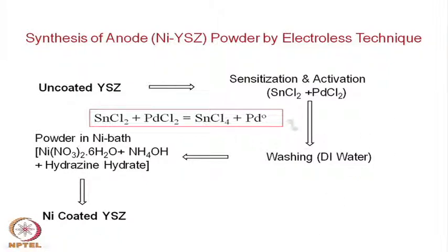Here we are not randomly mixing the two phases together, but in a structured manner. In a structured manner we are putting the nickel coating on the individual powders. So, that is possible by this powder electroless technique.